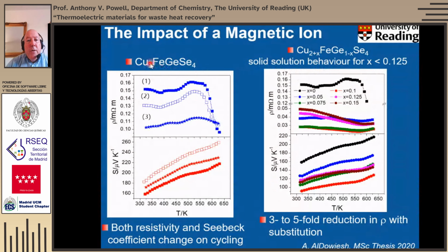There's one slight fly in the ointment with this phase, and we still don't fully understand this yet. If we do the measurements of the resistivity and the Seebeck on cycling, we find that actually the resistivity gradually falls from the first to the second to the third cycle. After the third cycle, it's more or less a constant value, and we see corresponding changes in the Seebeck as well. We're not quite sure why that is yet, because any thermal analysis that we've done suggests that the changes occur at significantly higher temperatures than we're getting to here.